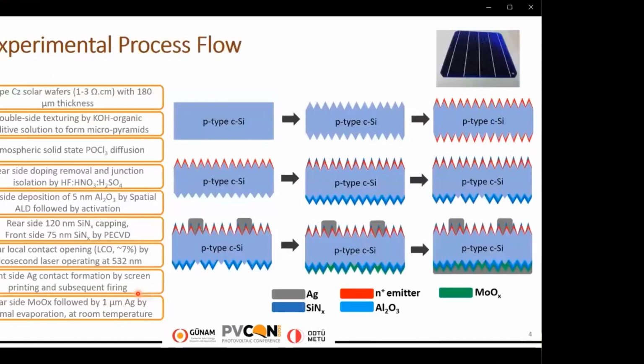So in our design, standard industrial processing and industrial equipment are utilized to fabricate PERC with molybdenum oxide/silver local rear contacts. We started with P-type Czochralski solar wafers with 180 micrometer thickness. Double-side texturing is performed to form pyramid texturing. Then the emitter layer is formed by phosphorus diffusion on both sides. A subsequent rear side doping removal is performed by single-side etching.